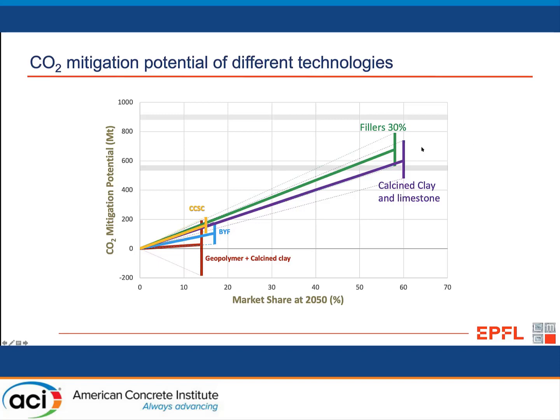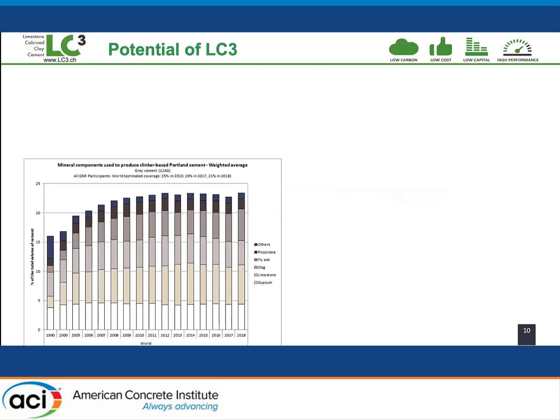So this is calcined clay and limestone, and then going to the concrete level to reduce the amount of cement used in concrete. So going back to this graph here, I said this level of substitution has stagnated in the last 10 years. Now, I think there's quite general agreement in the field that we could go down to clinker levels of at least 60% and probably even lower.